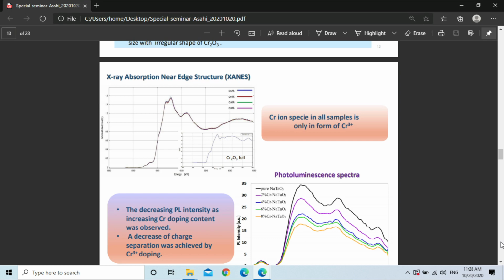For photoluminescence spectra measurement, we can see that for pure sodium tantalate and after doping with various amounts of chromium, the spectra intensity decreased when we dope with chromium. It means that doping with chromium can inhibit the recombination of charge carriers produced by the process. It means that this will help enhance photocatalytic activity.